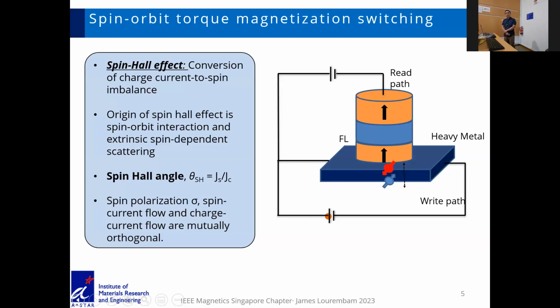So the materials parameter one would try to optimize in this kind of structure is the spin Hall angle, which is just the ratio of the spin current to the charge current. Another important parameter here is that the spin polarization, the spin current flow and the charge current flow are all orthogonal to each other. So this would lead to some critical requirements, especially in trying to switch a perpendicular magnet. It's easier to switch an in-plane magnet as compared to a perpendicular one. I'll get into details in the following slides.